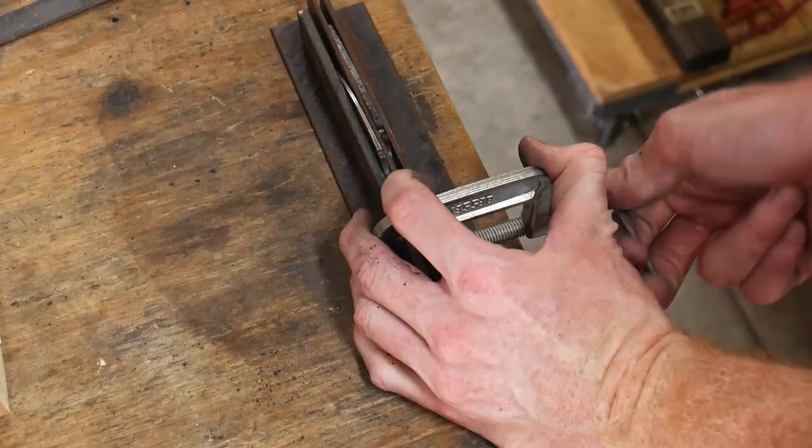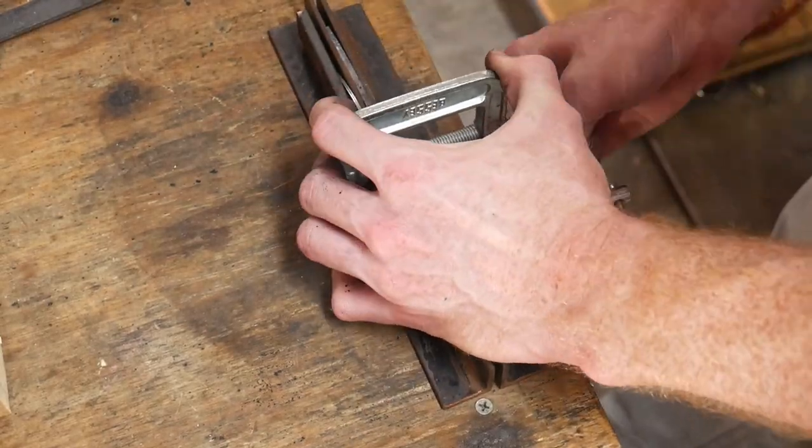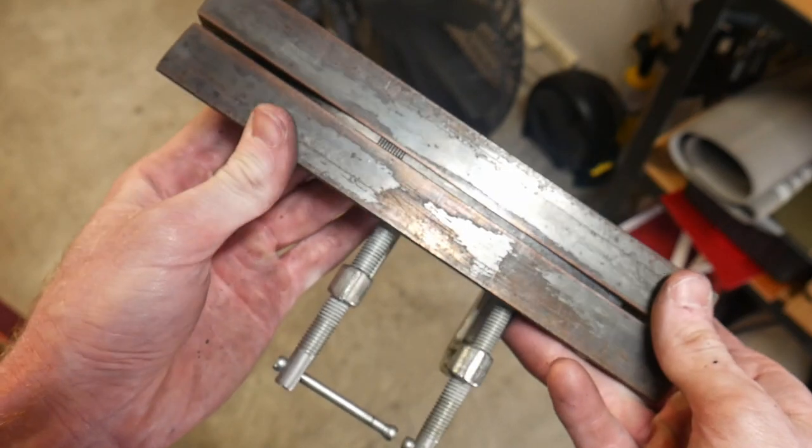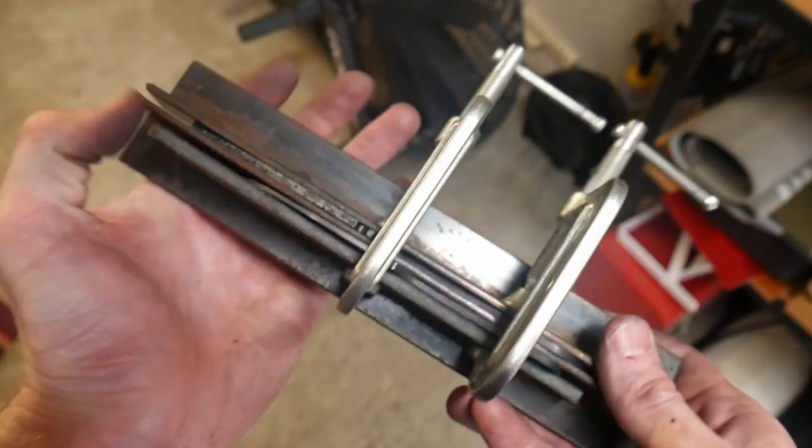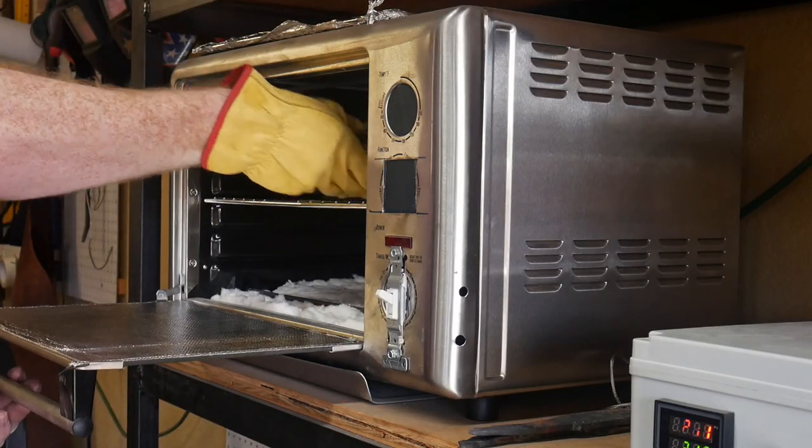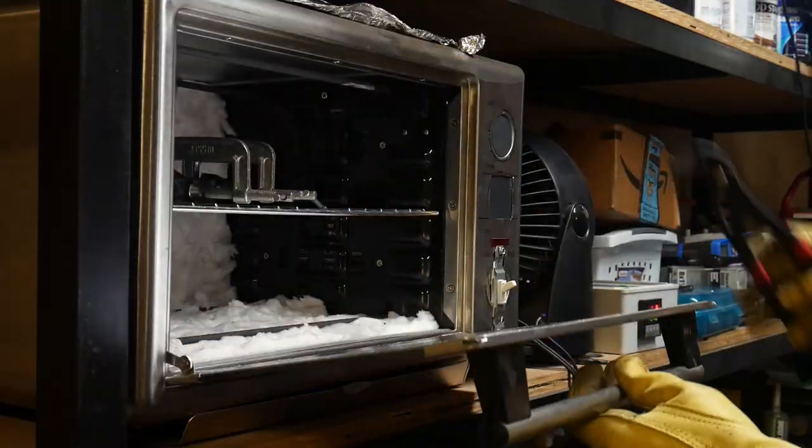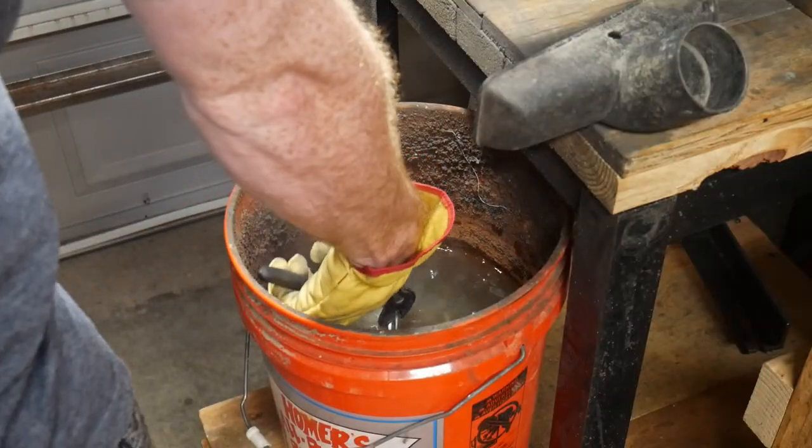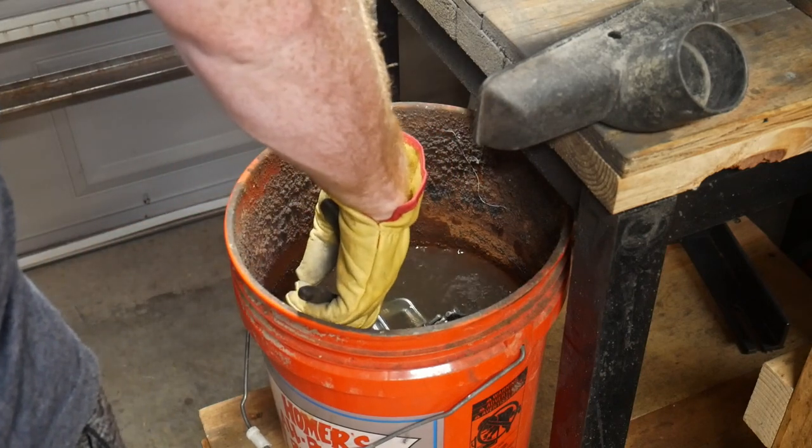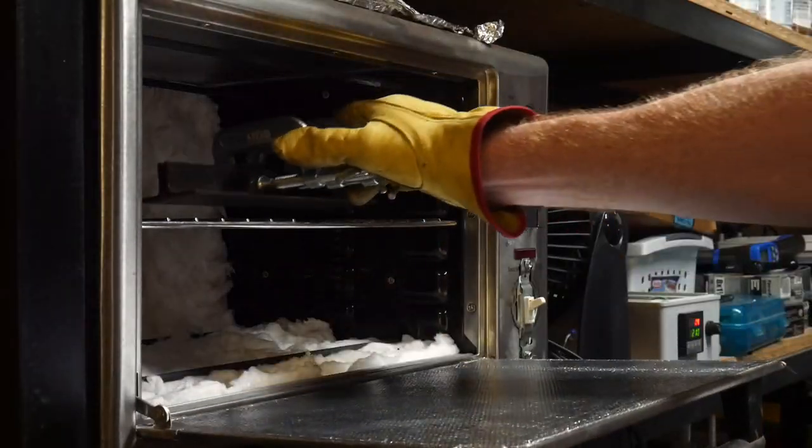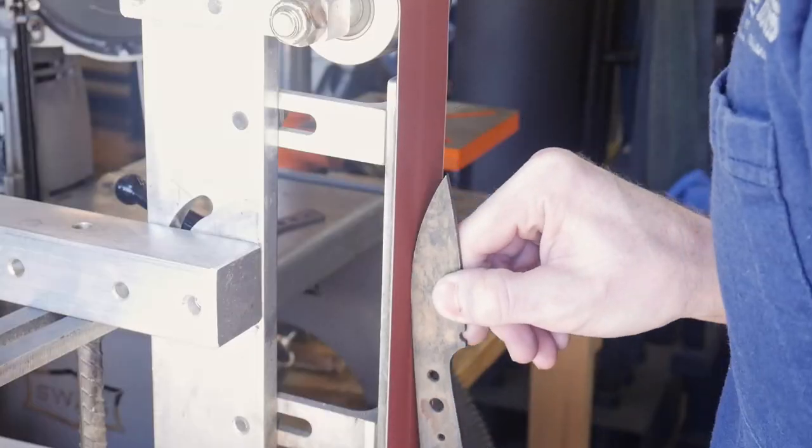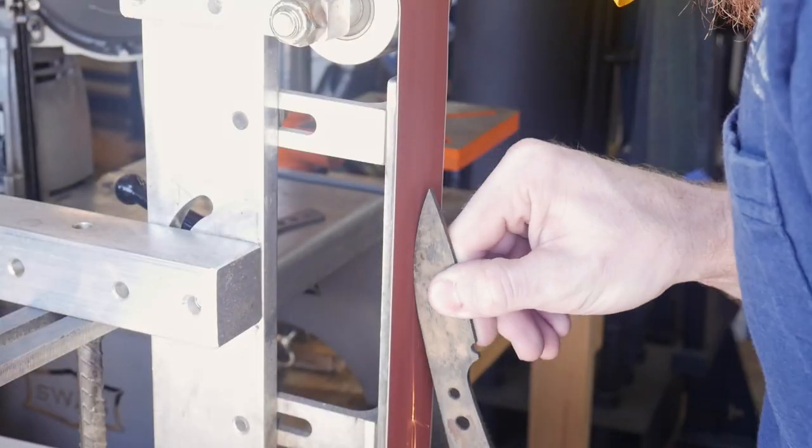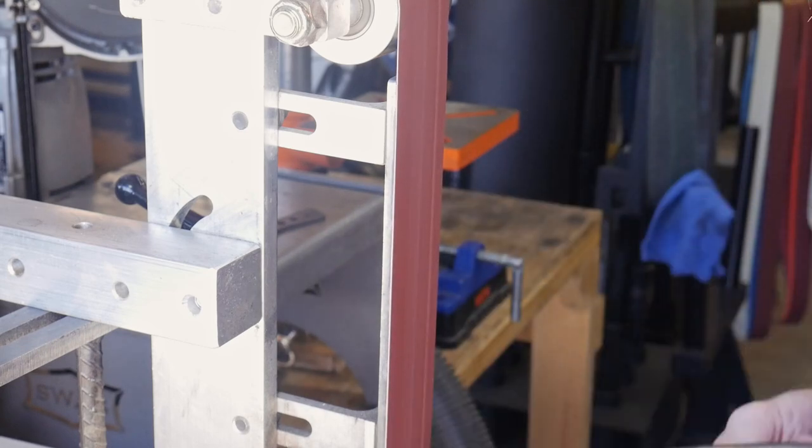We'll then get it clamped up between two pieces of angle iron for our tempering process. I'll be running two tempering cycles at around 211 degrees Celsius for two hours a piece. In between cycles, you can cool it to room temperature quickly in water and then put it back in for your second cycle. This does not negatively affect any of the properties of the blade.